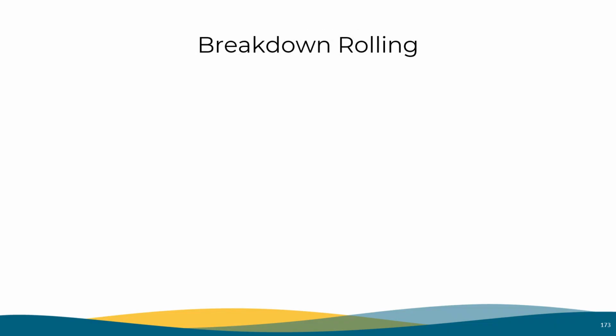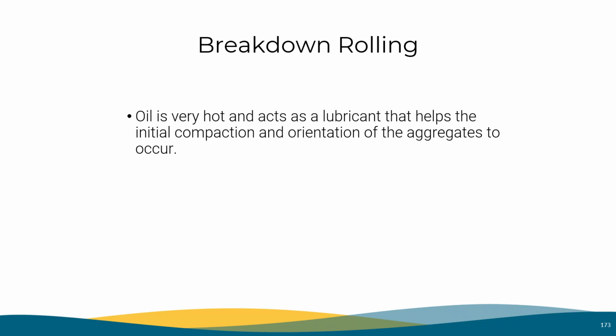During the breakdown rolling, the oil is still very hot and acts as a lubricant that helps the initial compaction and orientation of the aggregates to occur. This type of rolling is accomplished by always keeping a double steel drum roller right behind the paver.